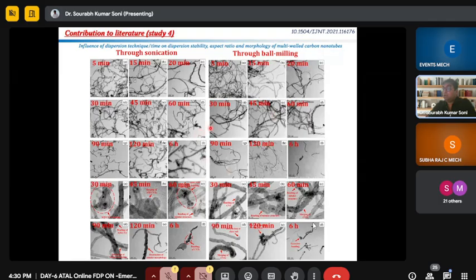In this TEM image, you can observe very clear microscopic images. This is the 5 minute, this is the 6 hour. So MWCNT shortening is there through sonication. Here through ball milling, there is very strong nanotube shortening. So there is a difference between sonication and ball milling, and you can clearly observe it through TEM because it is a high magnification microscopic image. Further, if you want to do HRTEM also, you can check whether there is any destruction in the morphology structure. You can analyze this kind of microscopic images for nanoparticles also. So if you are analyzing nanoparticles, my suggestion is to go for TEM.